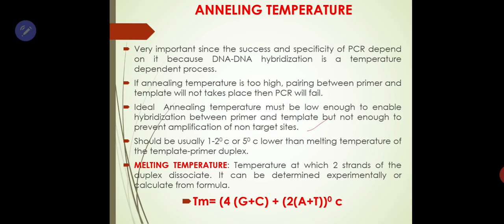So the annealing temperature should be usually 1 to 2 degrees or 5 degrees lower than the melting temperature of the template primer complex. So what is this melting temperature? Temperature at which two strands of DNA duplex dissociate. It can be determined experimentally or calculated from the below formula. Tm is equal to 4 into (G plus C) plus 2 into (A plus T) degrees Celsius.